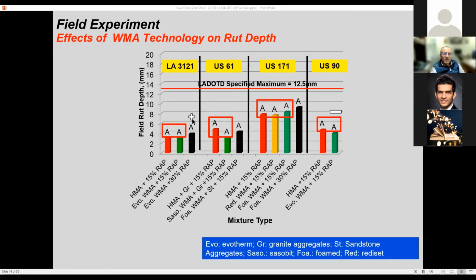And this is one of those things that I was saying earlier. This probably could be due to what's underneath that WMA. And this is something we're further investigating right now. And then if you look at the projects on US 61 right here, what you see basically is that the WMA had a slightly lower rutting as compared to the conventional one.